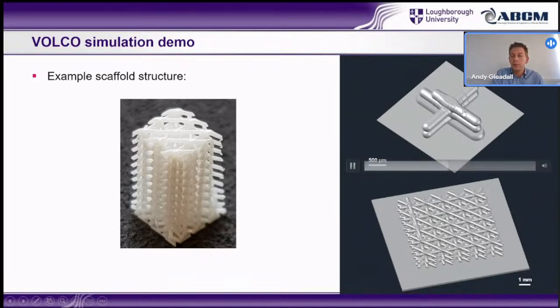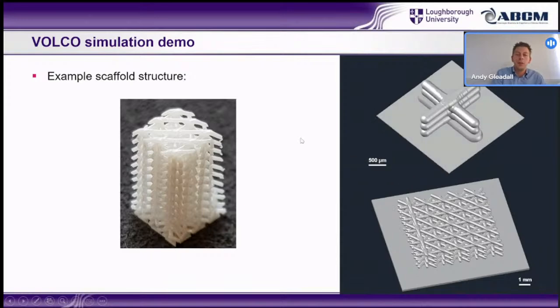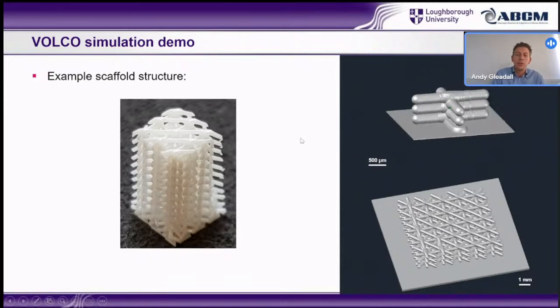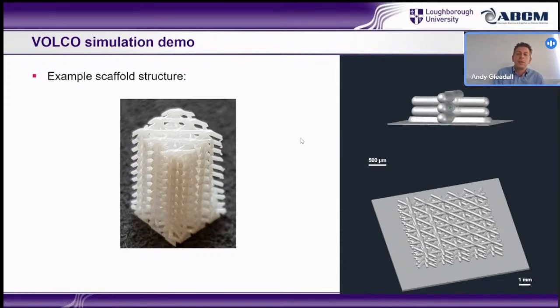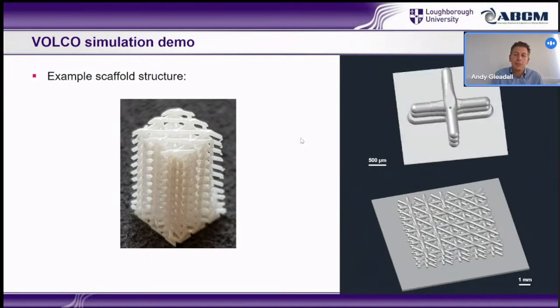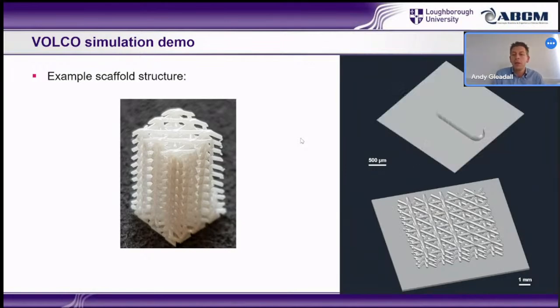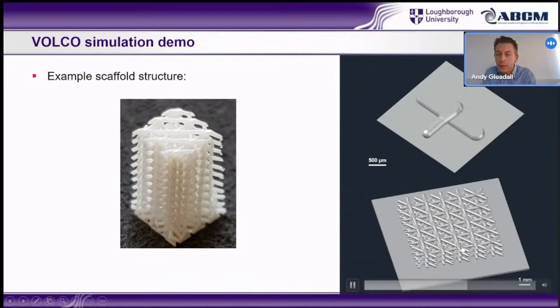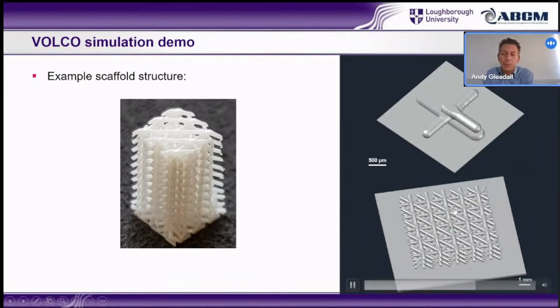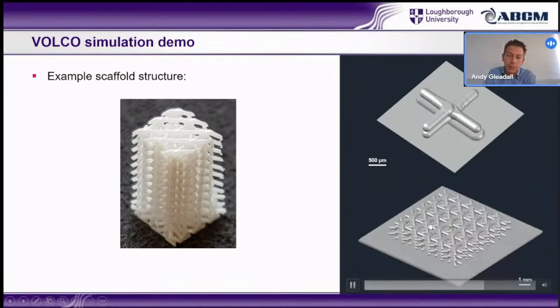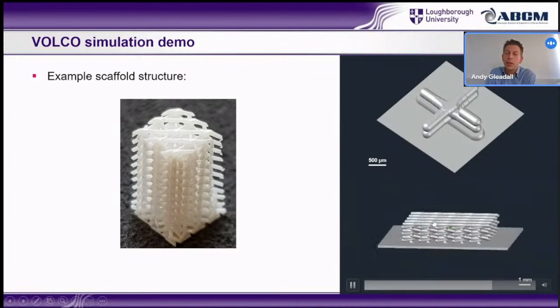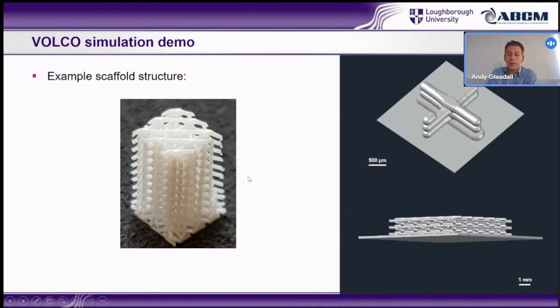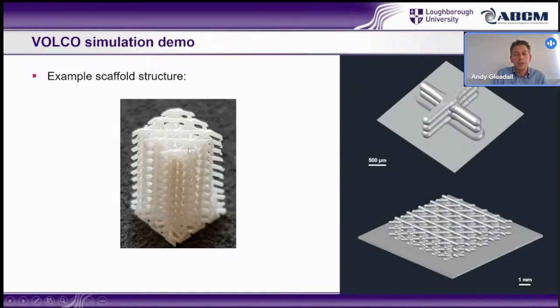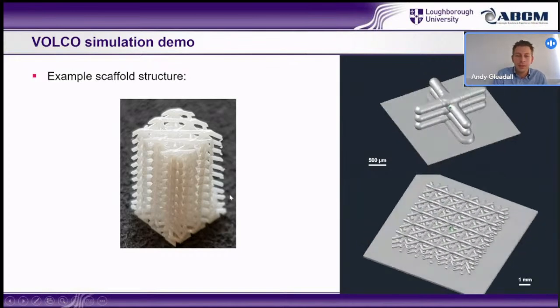So this is lots of tiny little steps. Each step is depositing a certain amount of material according to a kind of nearest distance criteria. So that naturally forms a spherical shape. And you can see at the bottom right, an animation of it being done on a much larger structure, but the same scale as what's shown here. So that's to simulate this kind of lattice structure.